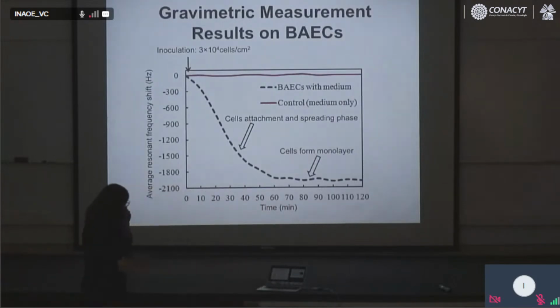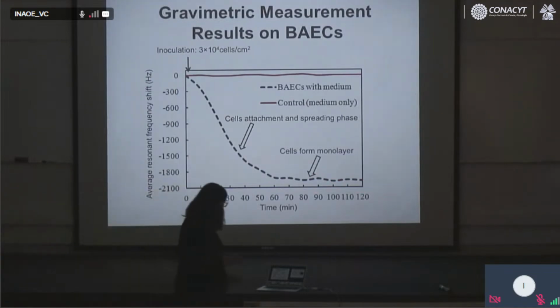Okay, so this is the information from the quartz crystal microbalance. You inoculate the cells here, this is when you introduce the cells on top of the quartz crystal microbalance. When you introduce the cells, the resonant frequency shifts. This is the highest value of the resonant frequency, and then the cells start to go closer and closer to the top electrode and attach to the top electrode of the quartz crystal microbalance, and so the resonant frequency is a little bit lower.